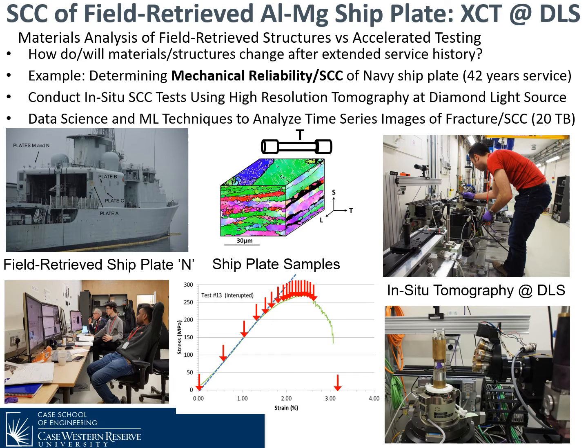And what we're particularly interested in looking at is how does fracture evolve in these materials. The microstructure is shown in the middle, and we've extracted samples in the T orientation to sample the grain boundaries in a specific way. On the far right at the top, one of our collaborators is putting the tension sample into the test fixture that's in the beamline. Eventually, we'll be able to test, as shown in the bottom right.